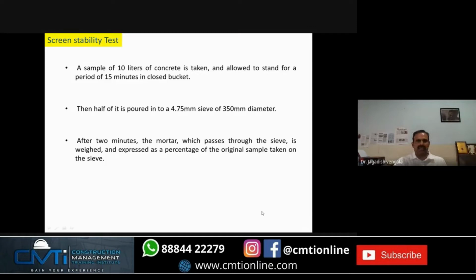This is a very simple test. You take 10 liters of concrete, keep it in a bucket, keep it for 15 minutes. You take the top 5 liters of the concrete, and then this top 5 liters, you pour it in a 4.75 mm sieve, and you sieve it. After 2 minutes, what will happen through the 4.75 mm sieve? Only the mortar comes out, passes through the 4.75 mm. You have the aggregate on your sieve. So you weigh the mortar sample. The percentage of mortar to the original concrete gives you the screen stability.